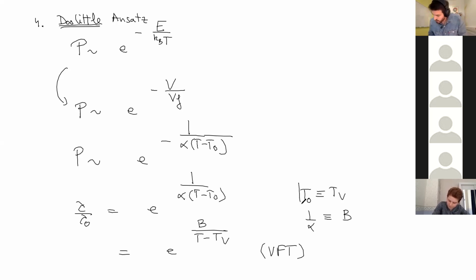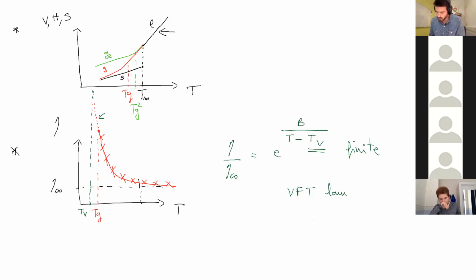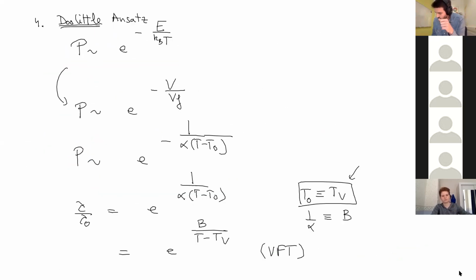All right. So the important thing is that now there is an identification between two concepts. This is a purely empirical temperature. I'm fitting the data of viscosity as a function of temperature, and it seems to explode. Now I extrapolate it as if it was really going to infinity, and it allows me to evaluate more or less a certain temperature for a hypothetical divergence of the viscosity. So this is empirical. And this is free volume. This is the temperature at which the free volume of the system vanishes. And so now you have an identification of the two. So perhaps the moment where the viscosity diverges is related to the vanishing of the free volume.